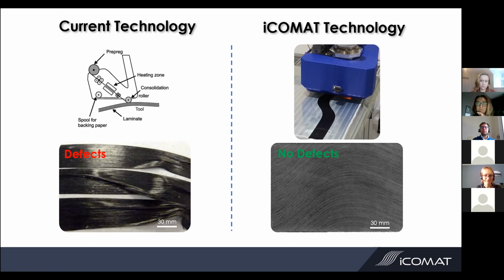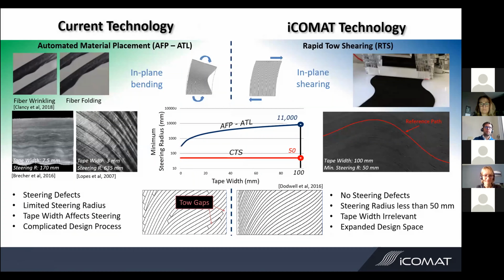Our technology, so RTS, rapid tow shearing, is a fundamentally different way of doing things. So we apply shear to the tape and not bending, so you can end up with steering without any defects, and it looks a bit like this. So again, to come back, AFP and ATL bend the tapes, which causes defects.